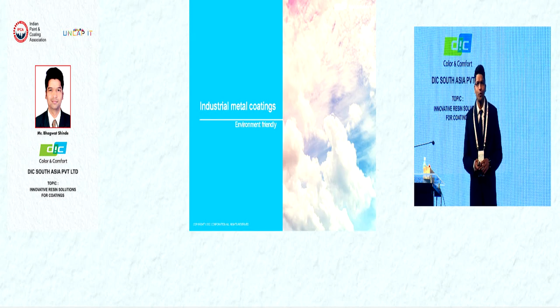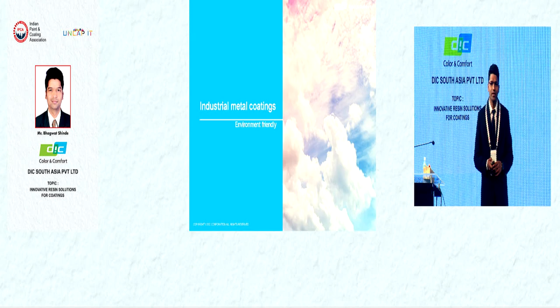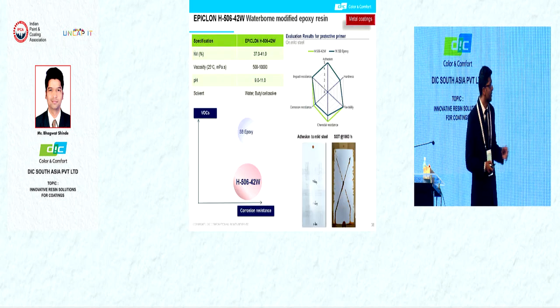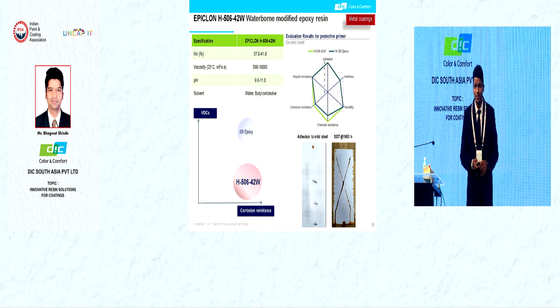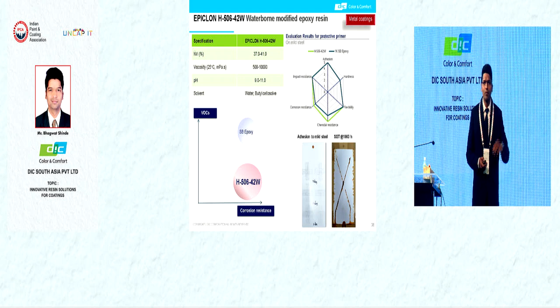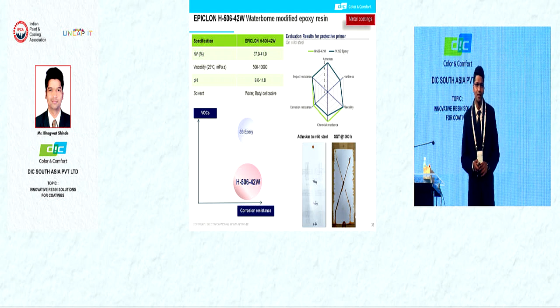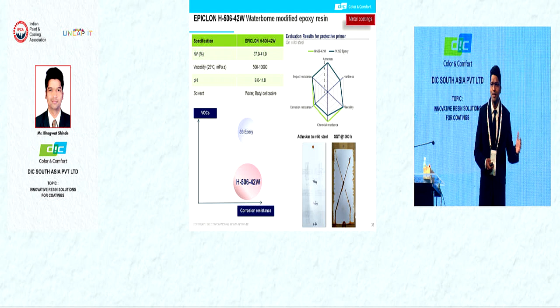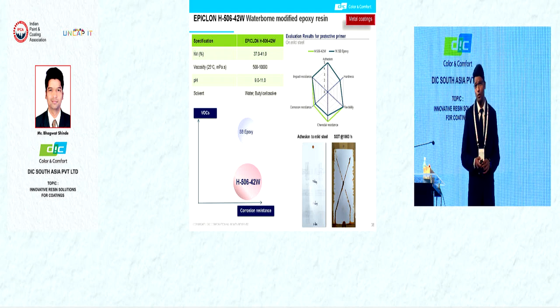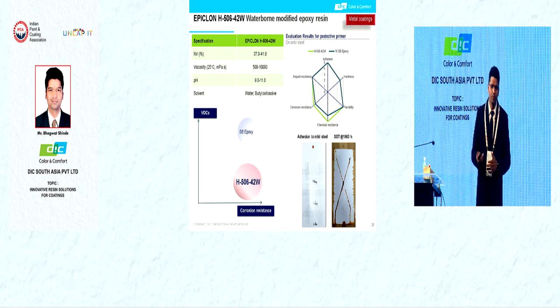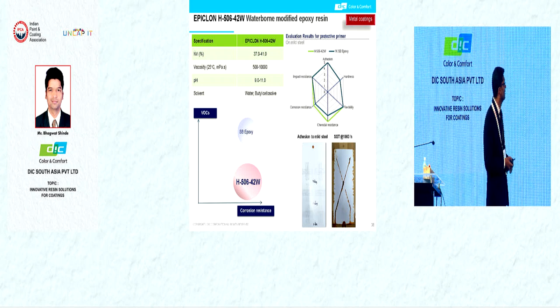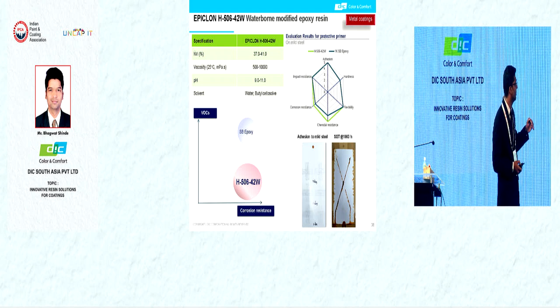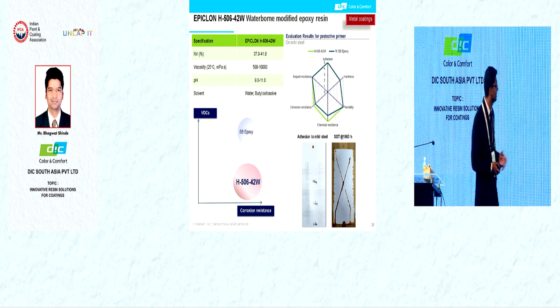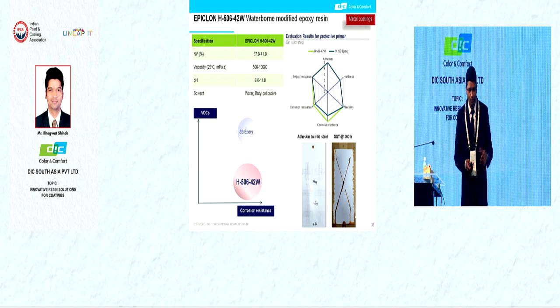The next one, I would like to introduce the eco-friendly products for the industrial metal coatings. Here is the Epiclon H50642W. This is the waterborne epoxy resin we recommend for primer application in industrial coatings. This is water based, so it has low VOC compared to solvent base, and this shows similar properties to a solvent base epoxy primer. You can see here, the product shows good flexibility, corrosion resistance, hardness, and impact resistance, as well as good adhesion to the metal.